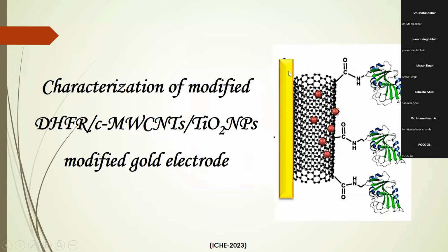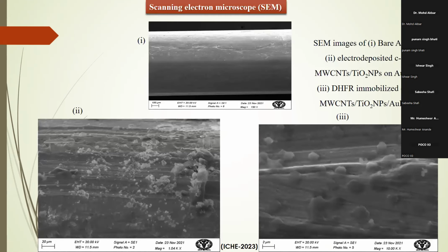To confirm the electrode deposition and the immobilization of the enzyme, characterization was done. Here scanning electron microscope was used to confirm the deposition and immobilization of the enzyme. Here the bare electrode showed no deposition of any other material, and here you can see the second figure that shows the composite nanotube modified gold electrode, and in the third you can see the globular like structure that confirms the presence of DHFR immobilized on the composite modified electrode.